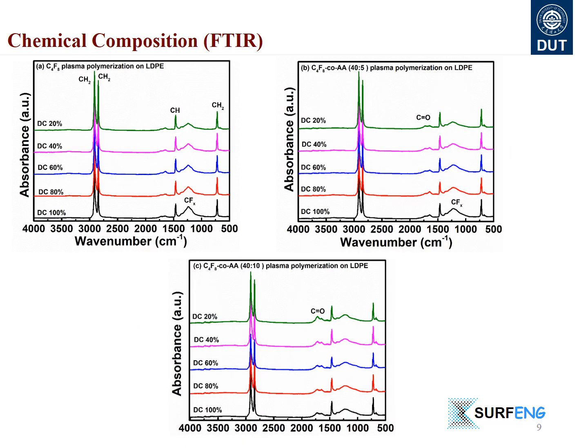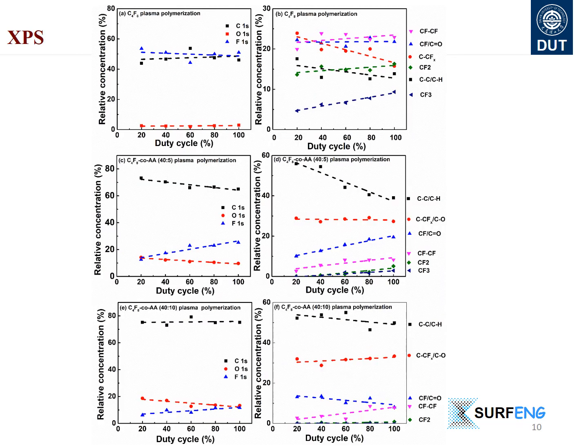The peak height of fluorine-containing groups decreases by lowering the duty cycle. The decline in fluorine-containing groups suggests less free radicals are available due to longer off time at low duty cycle. The chemical structure seems to change as carboxylic groups appear and become stronger by lowering the duty cycle. The minor variation in fluorine and carbon elemental composition of octafluorocyclobutane plasma polymer coatings indicates no significant change by lowering duty cycle. The high intensity of CF3 groups at high duty cycle suggests that more intensive fragmentation of octafluorocyclobutane molecules occurs due to continuous availability of RF high power. These results indicate that high duty cycle favors CF3 groups, well known for low surface energy.